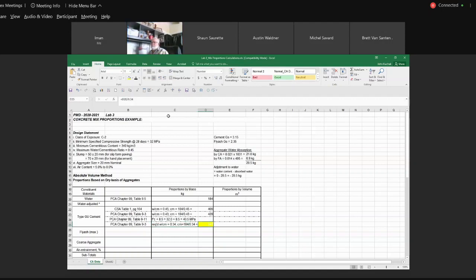So that means with 0.34 water cement ratio, I get 3 cement contents that are viable. Which one should I go with? Anybody? Which one do you think is going to govern? The 541 will. That's the one that tells us that at least with a 0.34 water cement ratio, we have to have 540, and we have to have 0.34 because now we're designing for 40.5 MPa, not 32.